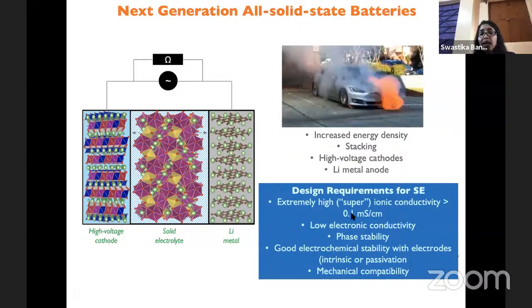So when we think of any large scale, we can think that if we have the solid state, it is very compact, it is highly energy dense because the stacking is very condensed, and we can use high voltage cathode, we can use lithium metal anode. But we need to think of the underlying mechanism and several other factors. So to design an ideal solid electrolyte, we need to consider a few criteria, like extremely high ionic conductivity, low electronic conductivity so that we can avoid short circuit. It should be stable in terms of phase, electrochemical or chemical. It should be mechanically compatible to make the device possible. So these are the requirements for the ideal solid electrolyte.